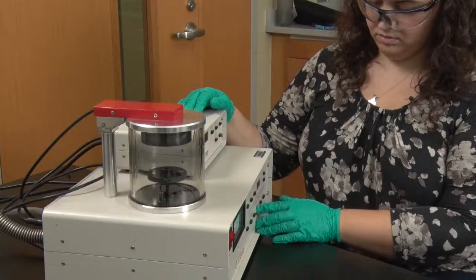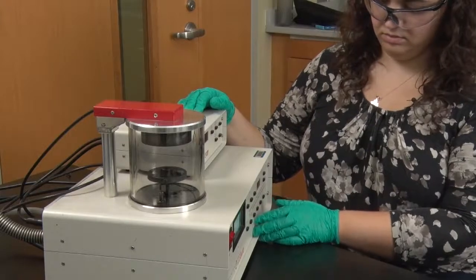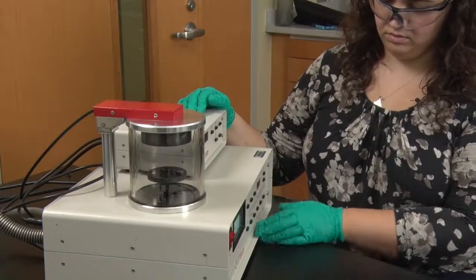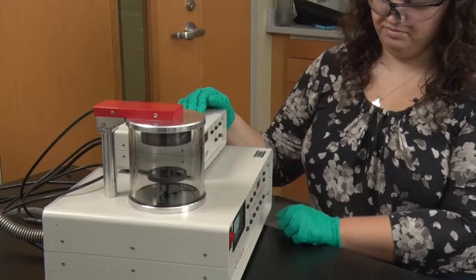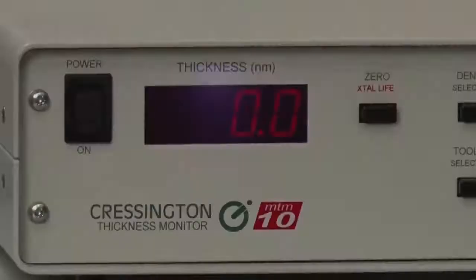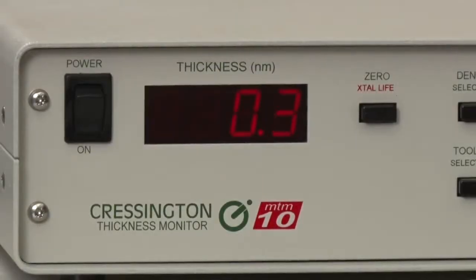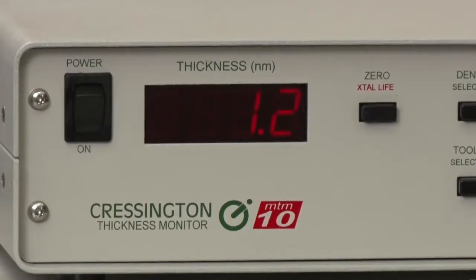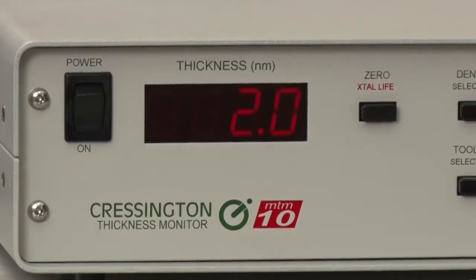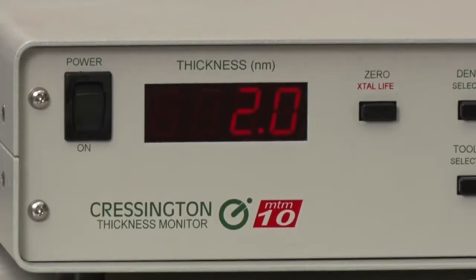A plasma is generated that removes material from the gold palladium target and deposits it everywhere in the chamber, including on my sample. It's easier to see this plasma if we turn off the lights. The readout from the quartz crystal microbalance lets me know how much material has been deposited. A 2 nanometer coating is usually sufficient to prevent charging. If your sample is conductive, or if you will be imaging in an environmental SEM, you can skip this sample coating step.